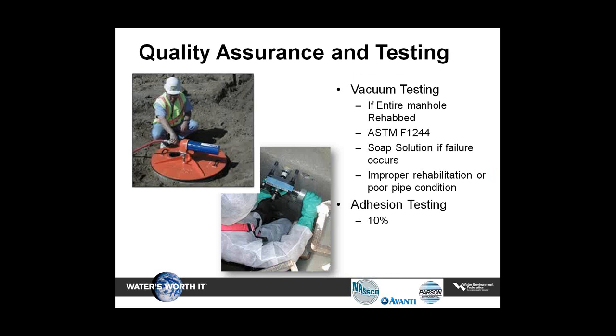If the entire manhole, including invert and pipe penetrations, is rehabilitated to as-new condition, then a vacuum test may be performed according to ASTM F1244. If the vacuum test fails, then the contractor shall spray the entire manhole with a soap solution and retest. Inspector shall determine if failure was due to improper rehabilitation or poor pipe condition or improperly seated plugs.